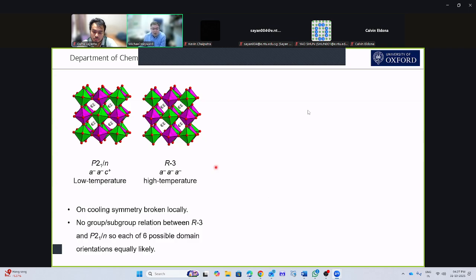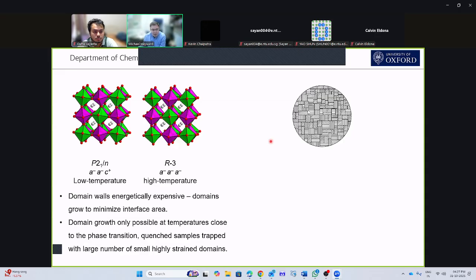So what happens when you cool the system down is you get a sample with lots and lots of small domains, where each domain corresponds to one of the 6 possible orientations. Now, it turns out that the domain walls, so the joins between these different oriented domains, are very high energy. We don't want to have that reorientation.